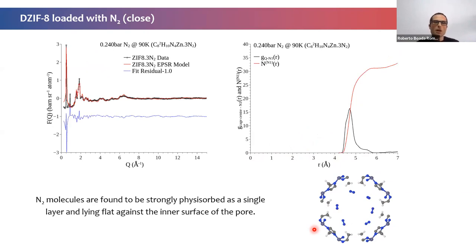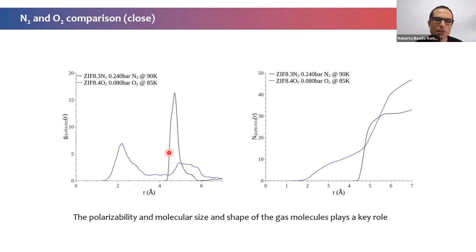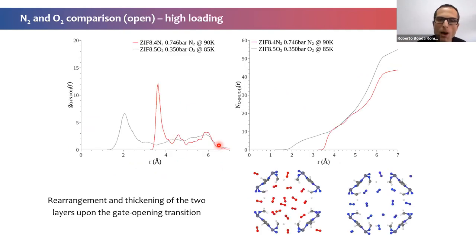When we change to nitrogen, at a low pressure with three nitrogen molecules per formula unit, we do see something rather different. We do see a fine nitrogen layer in the cage, covering the cage. And when we compare both, it looks like, in terms of the distribution of the oxygen and nitrogen atoms, the nitrogen is more well located, covering more closely the cage atoms, let's say. What happens